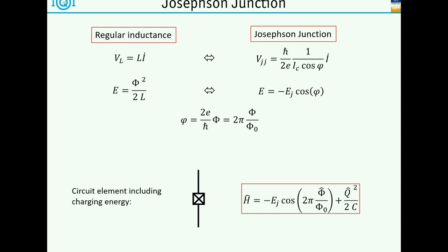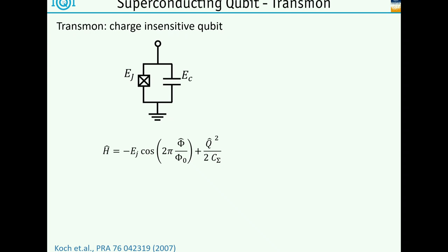It turns out it's very easy to make a qubit out of that. All I have to do is add another capacitance in parallel. So I take my junction, add a big-ish capacitance in parallel, and I've created my qubit. This is the so-called transmon qubit, and what is nice is it's a so-called charge-insensitive qubit, meaning even if there are fluctuating charges around because of unwanted defects and surface defects, this qubit doesn't care about it. It will still be a very, very good qubit.